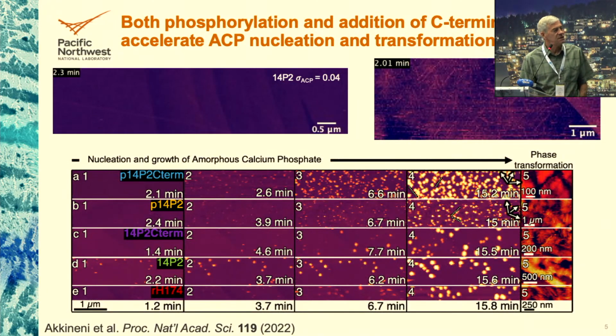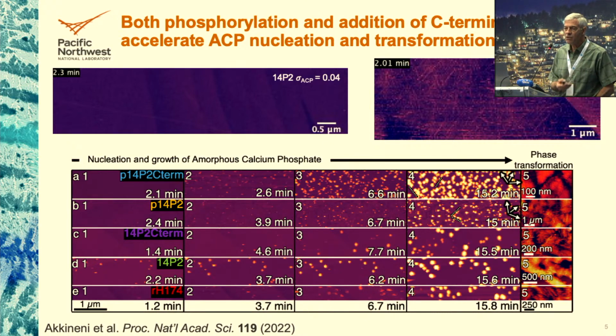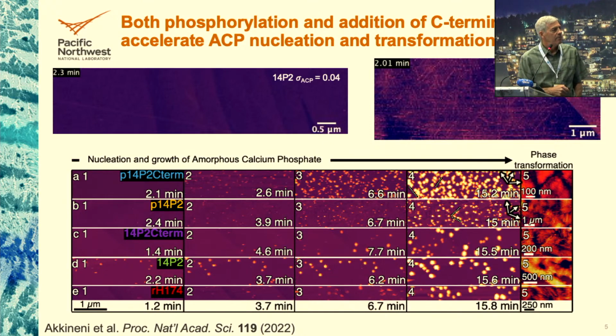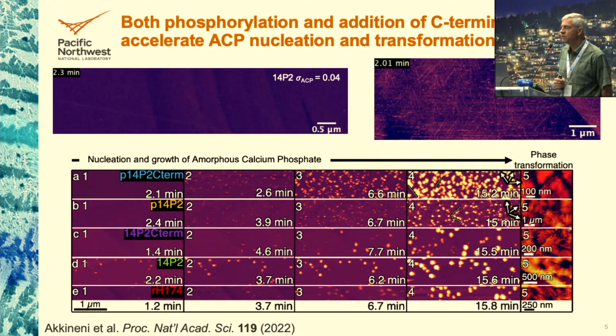So Susrit did this for all of the sequences at multiple concentrations, supersaturations, and you can see how they mineralize at different rates. And eventually, these last images are actually late in the experiment when you can observe the phase transition from this initial phase, which turns out to be amorphous calcium phosphate, to the hydroxyapatite phase. And I should have mentioned that it's largely believed, and there's good evidence, that in the tooth the first phase to form is the amorphous phase, and it later transforms to the crystalline phase. I also should say that this ribbon motif provides a natural motif for creating nanowire-shaped mineral, and so it's kind of exciting to think that it self-assembles into these ribbons. They would naturally drive the formation of ribbons of hydroxyapatite, which they do in our experiments.